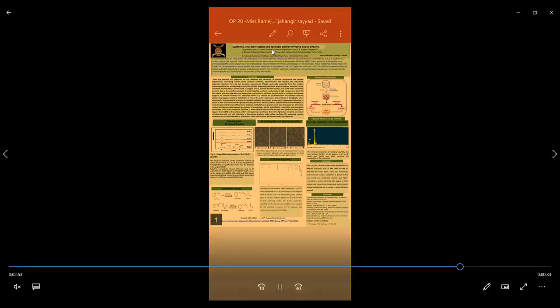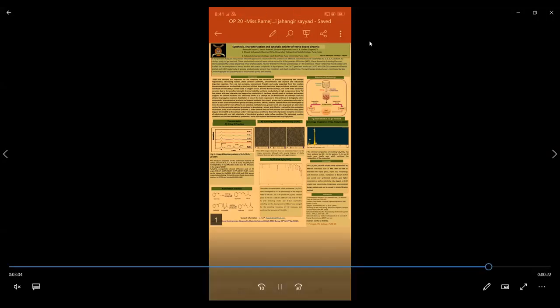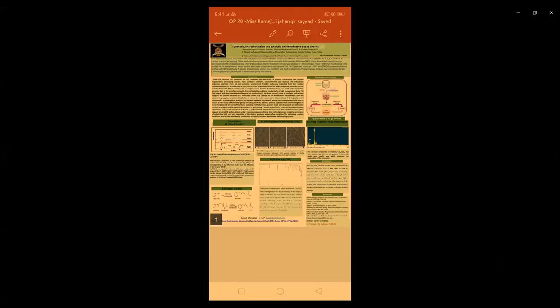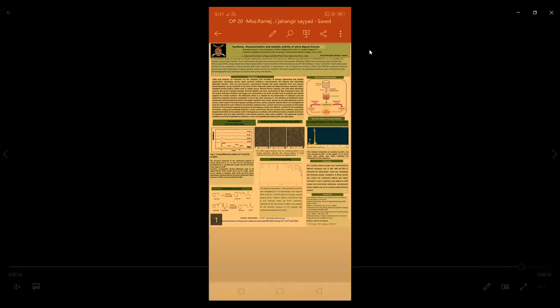After all this study, it is concluded that the SEM and EDX data confirmed the catalyst was in nano form, and this is also confirmed by the XRD analysis. Acetylation of benzyl alcohol using the catalyst gives higher conversion as well as selectivity. The yttria-doped zirconia gives maximum results due to its nanocrystalline size as well as purity, and can be reused by a simple filtration method without significant degradation of catalytic performance.